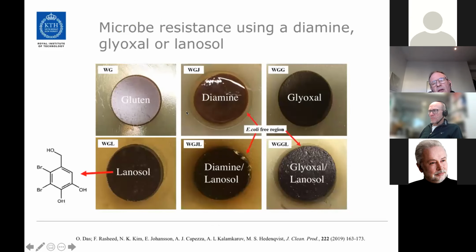That's what you would expect also. Now, if you don't want it to degrade too rapidly, this is essentially food, so you have microbes that can be a problem, or mold. But you can tackle that by adding chemicals to it, so you actually make it antimicrobial. We've been using, for example, bromophenols, which is not something one looks at at the moment because of its problem. We don't want to use it. But this is actually a naturally occurring bromophenol, which is quite unstable, but it has very good antimicrobial properties. So it's a natural bromophenol, and it's also degradable since it's a natural one.